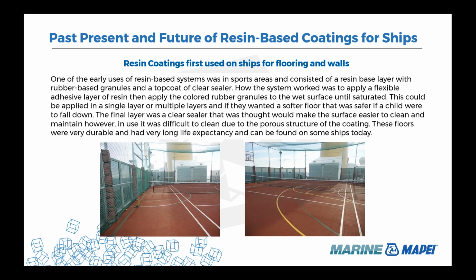How it works is they would apply a flexible adhesive layer to the deck, and then they would apply colored rubber granules to the wet surface until the surface was saturated, kind of like a sand broadcast to refusal. This could be applied to the ship in a single layer or multiple layers to get a softer floor that would be safer for children's play areas.